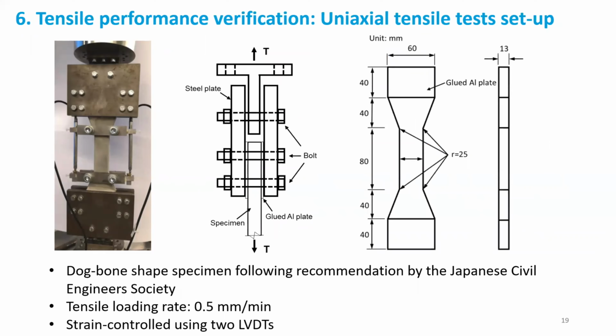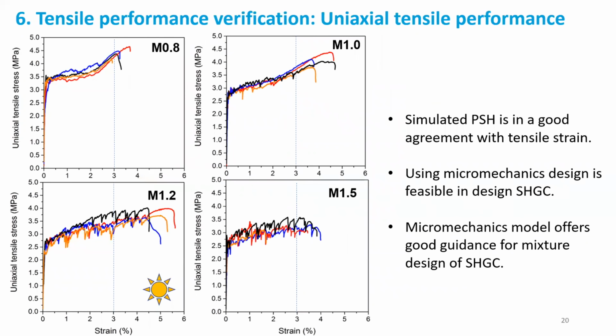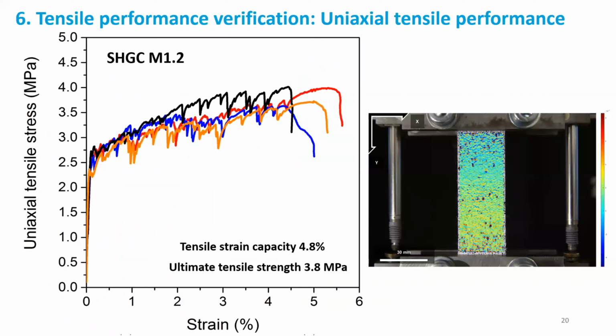And finally, we use the uniaxial tensile test to evaluate the tensile performance predicted by the micromechanical modeling. All the results are shown in here. It is found that the simulated PSH, especially the PSH strength, is in very good agreement with the tensile strain capacity. And more importantly, as predicted, mixture 1.2 yields the best performance. With this, we also conduct the DIC analysis on the multiple cracking behavior, and this shows that this mixture almost shows saturated multiple cracking. So with the tensile strain capacity of 4.8% and ultimate tensile strength of 3.8 megapascal, this SHGC mixture seems very promising and is also comparable to conventional SHCC with moderate strength.